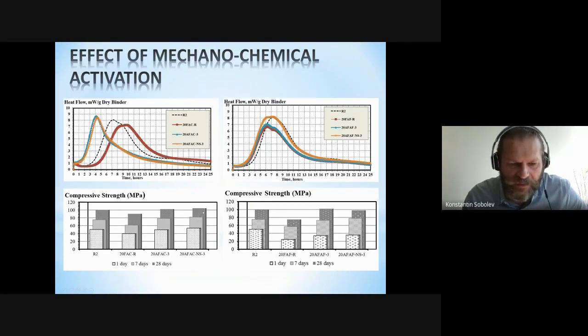Systems with nano seeds were extremely fluid, and you can potentially have further strength improvement by control of water to cement ratio, but it was not the aim of the study. It was important for us to demonstrate that these products can really enhance the performance, and keeping water to cement ratio constant was the important parameter to keep.